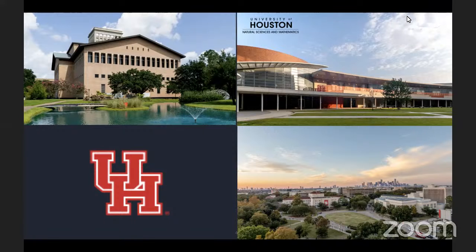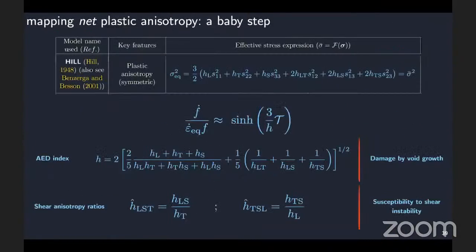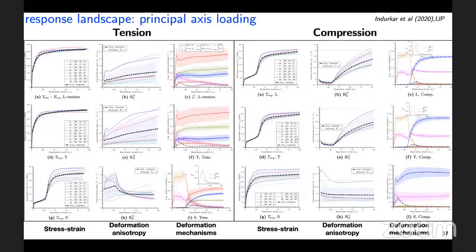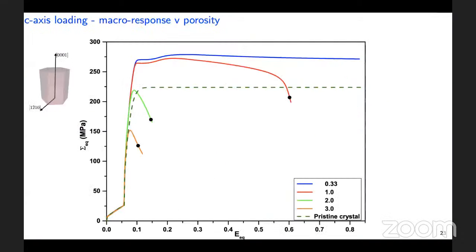The first one pertains to the type of void coalescence, because you didn't mention that clearly in the simulations where the extension twins are activated, where your C-axis is along the primary direction, right? So once the extension twins engulf a major portion of the cell, you start activating pyramidal C plus A and basal. But how are these voids going to coalesce? What do your simulations say?